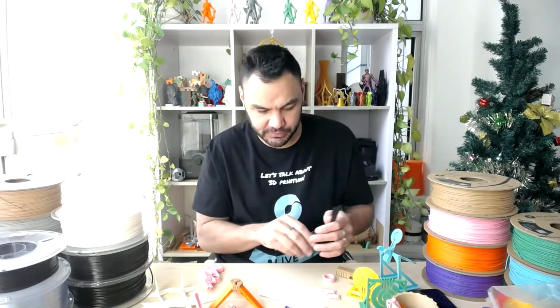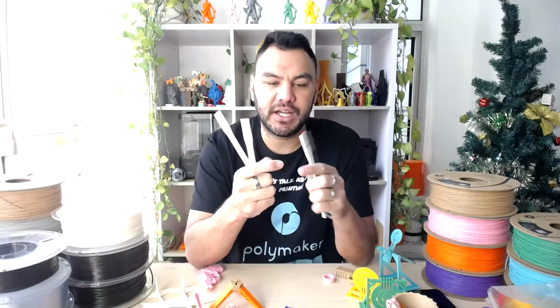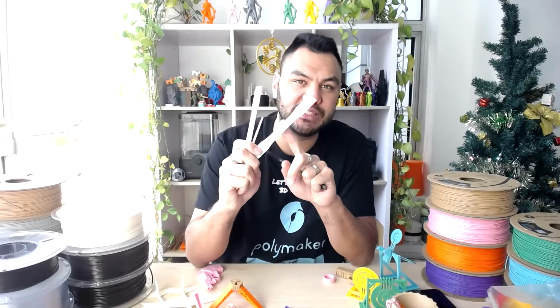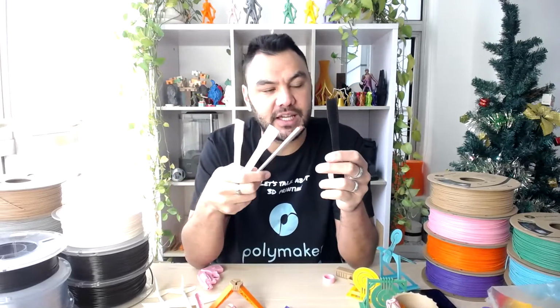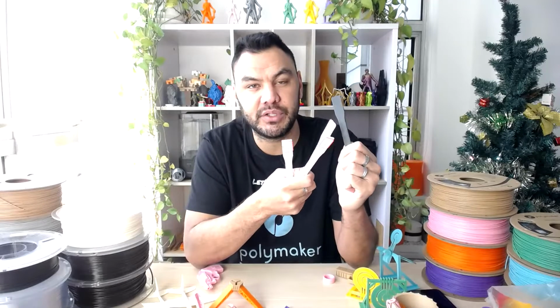Yeah, we have this one. When it comes to polycarbonate, we have the Polymax PC, a top version of polycarbonate. We have Polylite PC, a more regular polycarbonate that comes in transparent. We have a PC-ABS blend, more for processability. And we have a PC-PBT blend. The advantage of PC-PBT that comes from the PBT, compared to PC, is the chemical resistance and the low temperature toughness. At minus 30 degrees, you keep up to 70% of its toughness, whereas regular PC at minus 30 degrees will be around half or less than half of its impact strength. Any polymer becomes very brittle at low temperature, so that's one of the advantages of PC-PBT. So yes, we do have one.